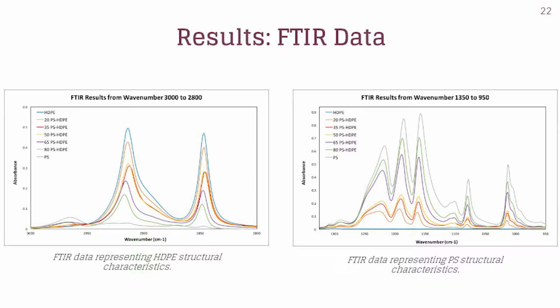The FTIR also shows that there really is just polystyrene and HDPE in our samples because there is no presence of peaks occurring at any other areas. And every sample showed a peak in absorbance at the same point, so there was no outlying data that would have shown the presence of contaminants.